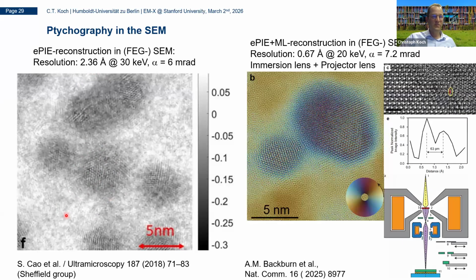More recently, actually very recently, there's this publication by the group of Arthur Blackburn, who showed really sub-angstrom resolution down to 0.67 angstrom resolution in this microscope, which has a twin pole piece. So it's called an SEM, but I would want to call it a low voltage TEM. But it also uses TEM holders actually to load the sample in there. But at 20 kV, this is quite an improvement in resolution beyond what the microscope can actually do.